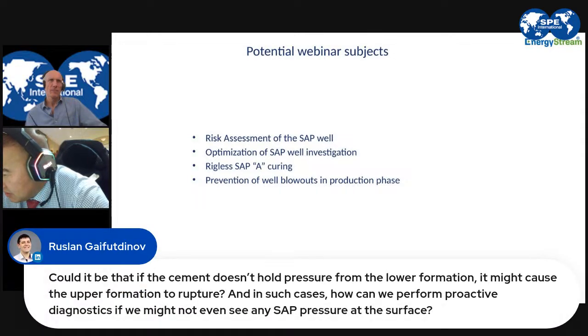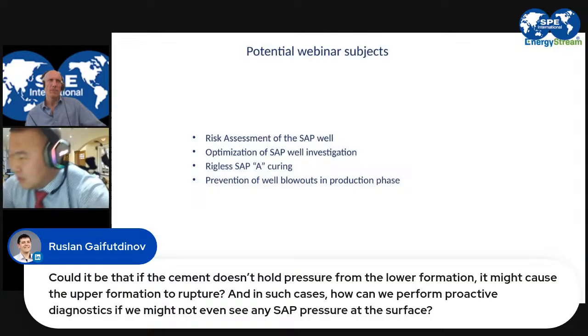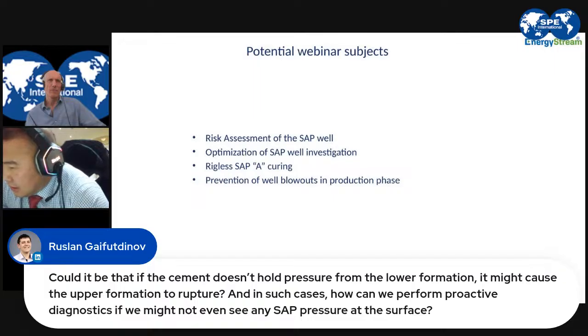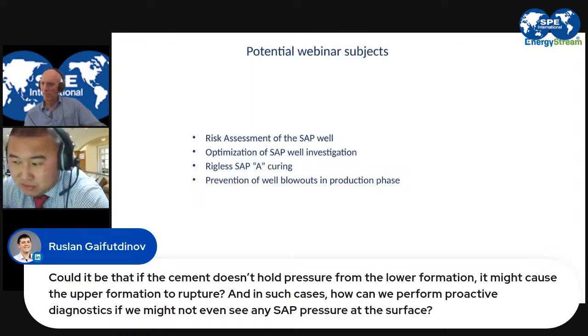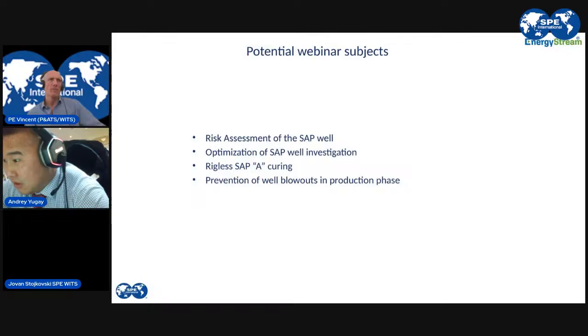And could it be that if the cement doesn't hold pressure from the lower formation, it might cause the upper formation to rupture? And in such cases, how can we perform proactive diagnostics if we might not even see any SAP pressure at surface? Let me try to understand the question. So basically, we don't see any pressure indication at surface, and we have a cement degradation at the bottom, and the pressure from the bottom migrated to the upper through the original cap rock that initially was okay, but since we drilled the well, we created a path and the isolation was not good, and we created communication.